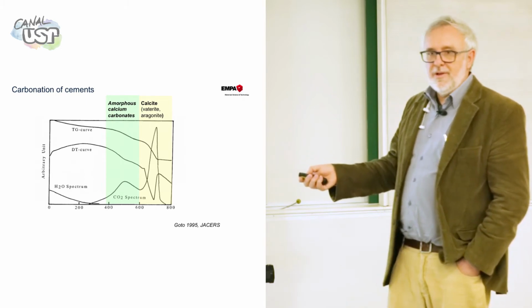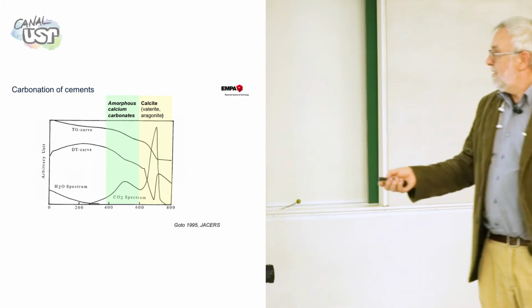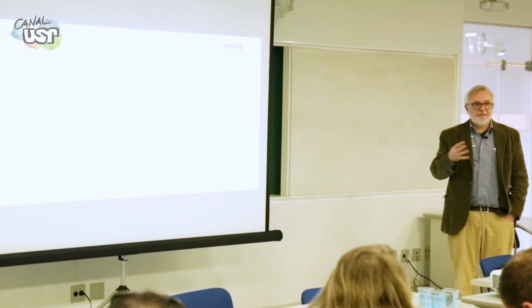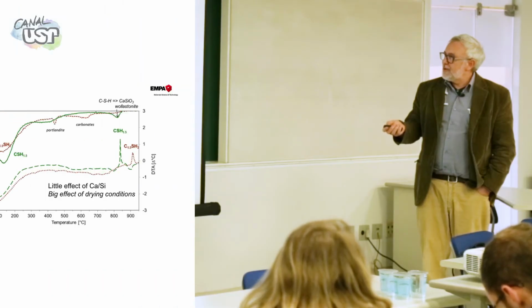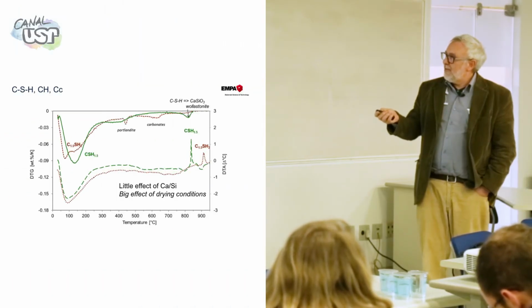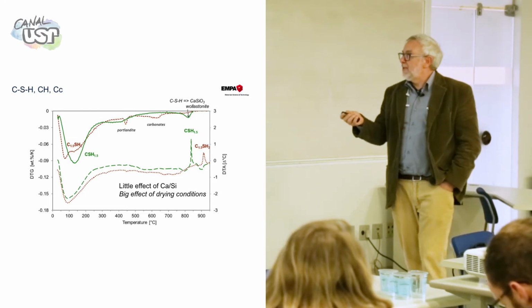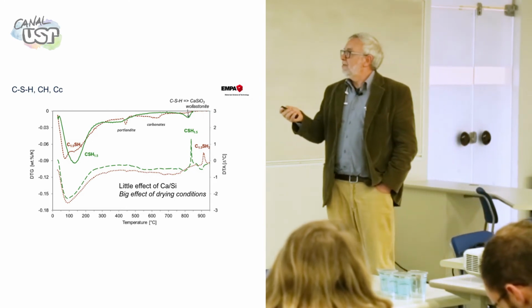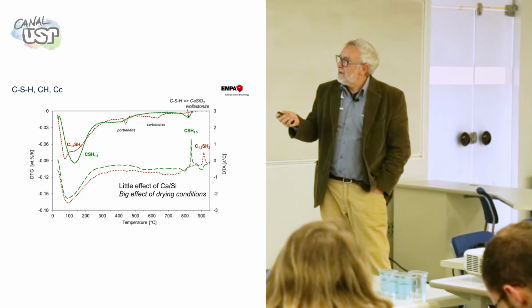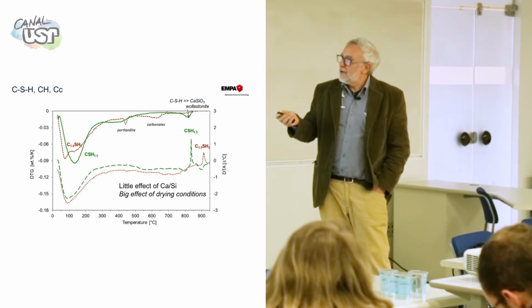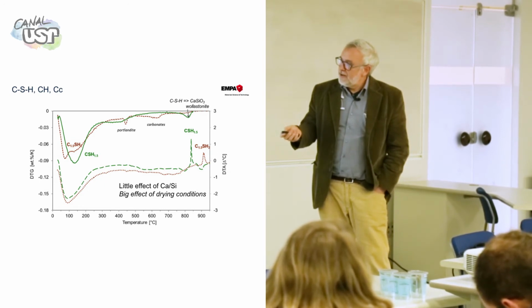That is exothermal. You can see in DSC, very, very easy. So when you have accelerated carbonation, you don't apply the 600 degrees rule. You have to look carefully at what you are going to do. This is CSH. The composition of CSH is from wollastonite, a mineral that is calcium silicate oxide. And then you hydrate, you get CSH, things like that.